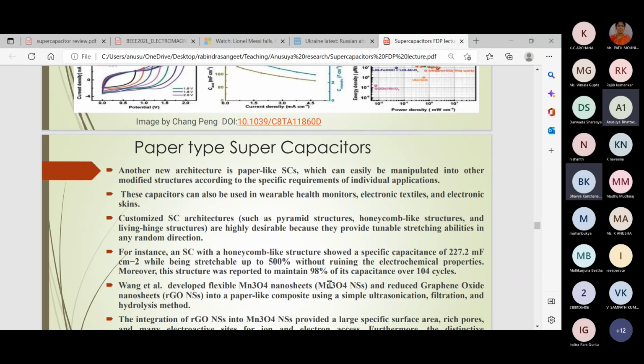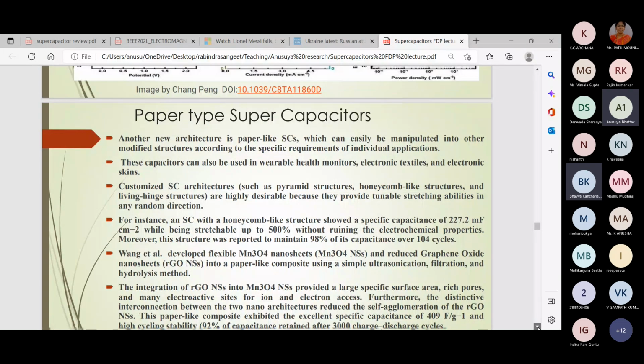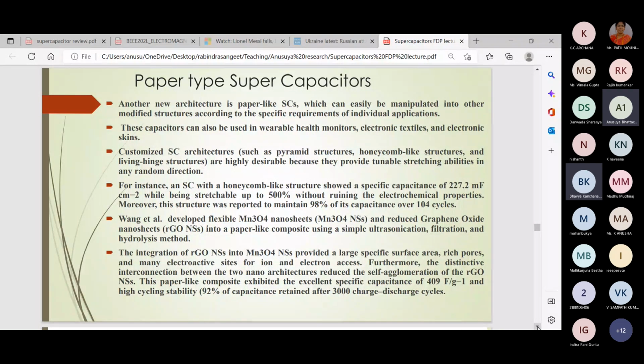Similarly, Wang et al. had developed flexible manganese oxide nanosheets and reduced graphene oxide. It mixed two different types of nanosheets into a paper-like composite using a simple ultrasonication, filtration, and hydrolysis method. Ultrasonication is one good method to disperse two nanomaterials together, because it breaks down. See, nanomaterials, they don't like to remain nanomaterials because that surface area is very high. They tend to bond together, they tend to stick together more, because the effective active surface energy is higher. So that tends to cause them to agglomerate, and ultrasonication can actually help break it down and separate it.